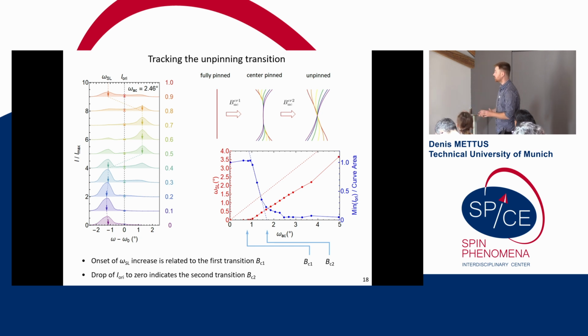What we do is track the amplitude of the skyrmion peak motion, and track the minimal intensity at the center, which gives you the amount of skyrmions which are always looking in your static field direction. We plot them on top of each other, like here. This is the amplitude of the skyrmion rocking peak motion.